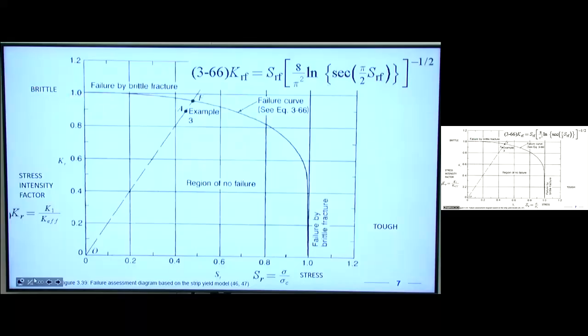And we don't look only at the stress for that. We have to look at the fracture toughness. And so on the y-axis here is another normalized value, 0 to 1. And instead of being stress, it's now the stress intensity factor for brittle fracture, right, which is these K values. And so if we normalize the one that we have by that effective one from the strip model, and we go 0 to 1, then at 1 we would expect a brittle fracture to occur. And so what the strip model allows is the drawing of this line between the two.